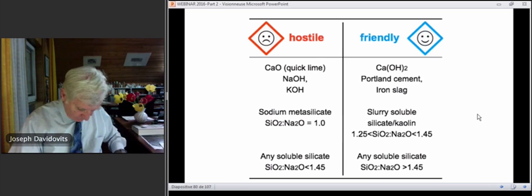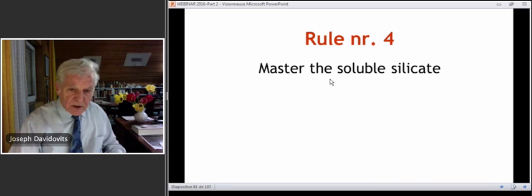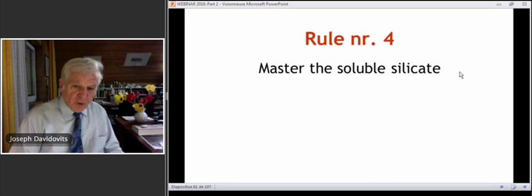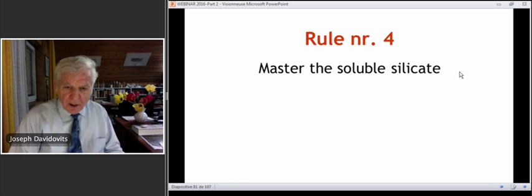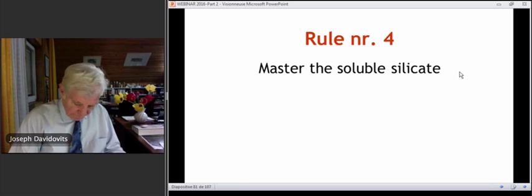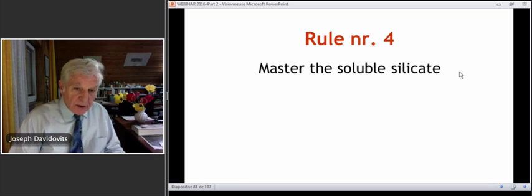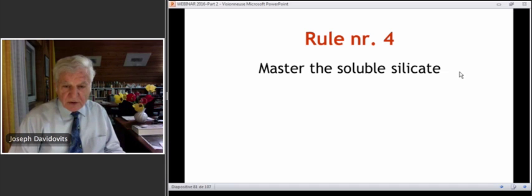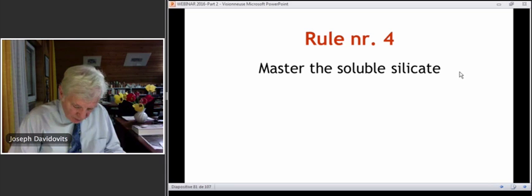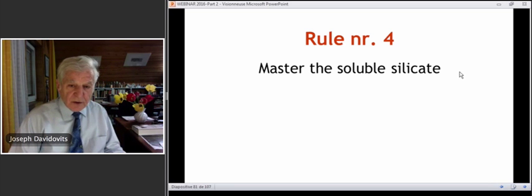Rule number 4, master the soluble silicate. Soluble silicate, this is water glass, period. We just adjust the ratio and no problem. Wrong. In 1978, when we started to study the making of the first geopolymer by reacting water glass sodium silicate with metakaolin, we had reproducibility problems. Between each bottle of sodium silicate water glass that we purchased, we had different viscosities. And we had to learn to understand what was going on in terms of the molecular makeup